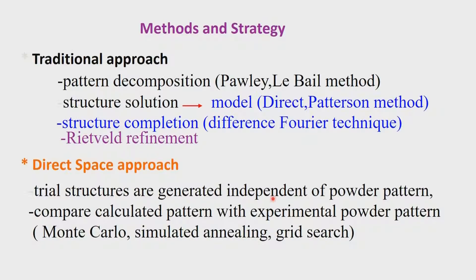What is the method and strategy we use? We know Rietveld refinement will help if we have a starting model, but how do we get the starting model? In any case we have to do the pattern decomposition, and there are two mainly available methods: one is due to Pawley and the other due to Le Bail. These two methods are already in the program EXTRA which we used.